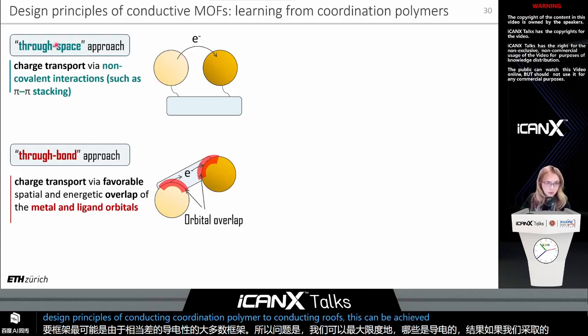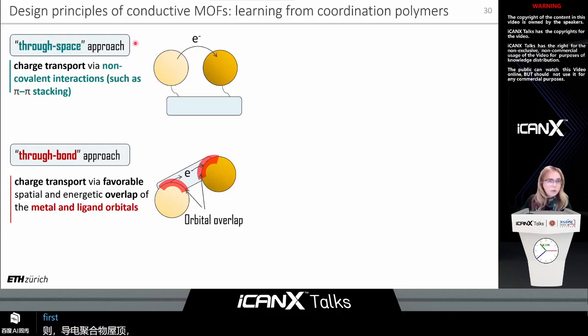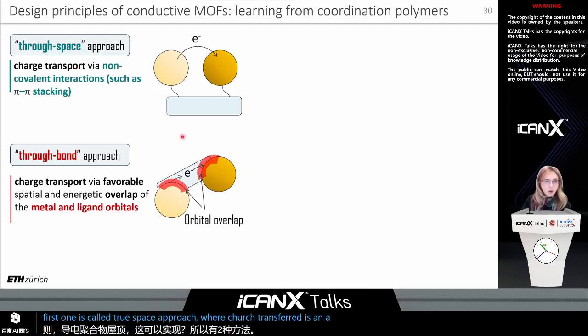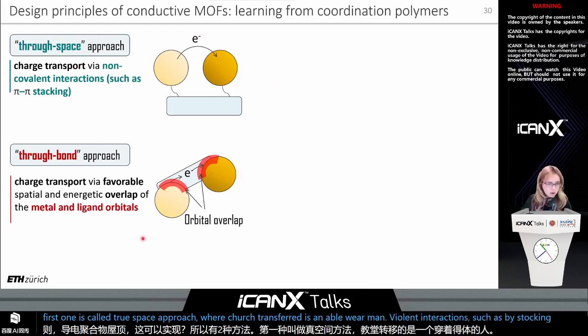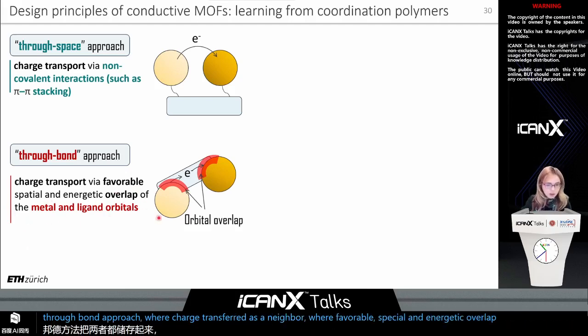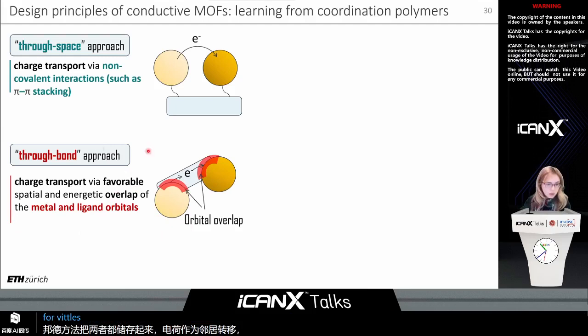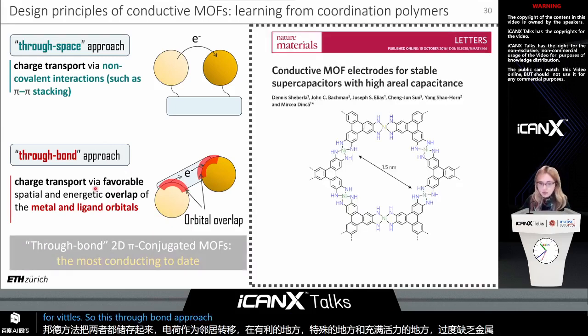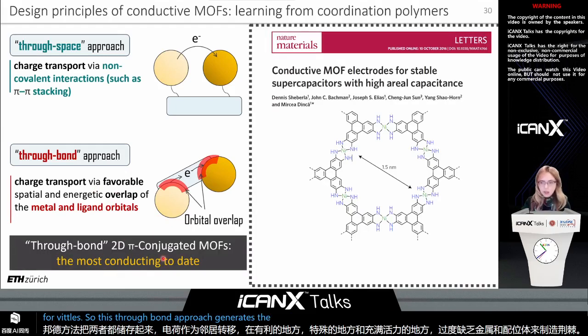So there are two approaches. The first one is called the through space approach, where charge transport is enabled via non-covalent interactions such as pi-pi stacking, or the through bond approach, where charge transport is enabled via favorable spatial and energetic overlap of metal and ligand orbitals. This through bond approach generates the most conducting metal organic frameworks to date.